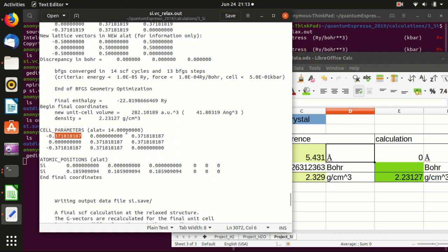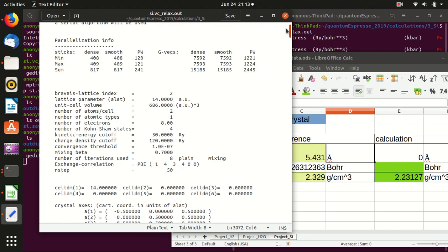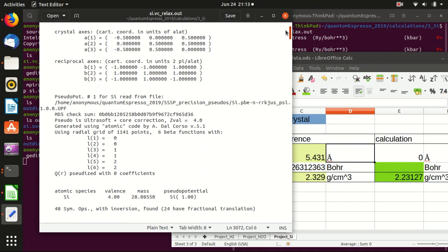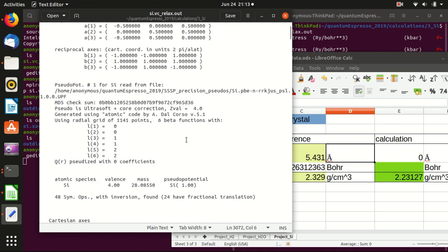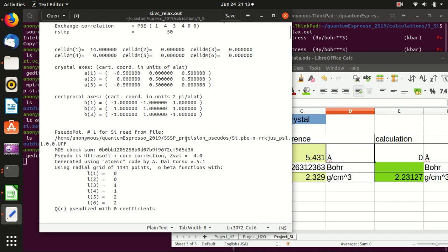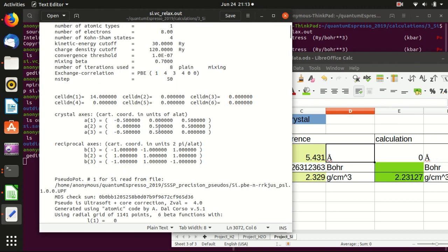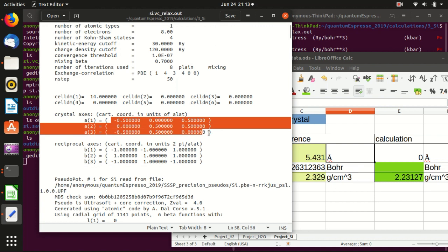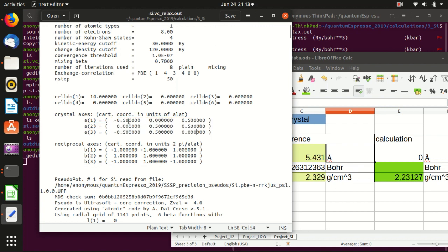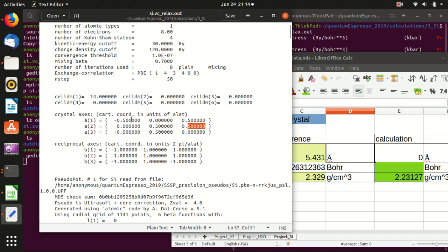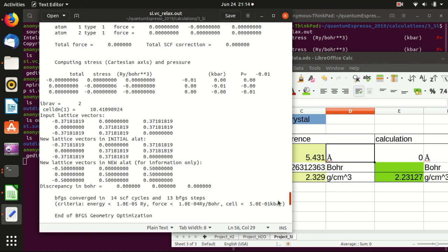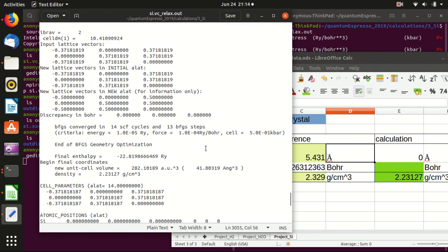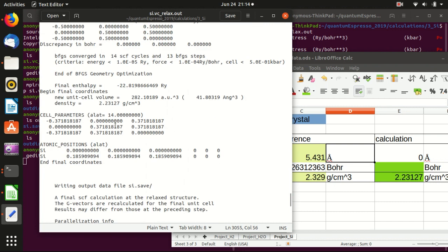Another thing is, so basically this is the cell parameter. It is written in a strange way. We can first go to the beginning. Because beginning, we know that this is a simple FCC lattice. So in a simple FCC lattice, it is written in this way. So we see that for FCC lattice, it is minus 0.5, 0, 0.5, 0, 0.5, 0.5, 0.5, 0.5, 0. If you remember from solid state physics, this is just primitive lattice vector. And so basically we, what we need to do is to divide the final result by this 0.5 and multiply by the alat number.